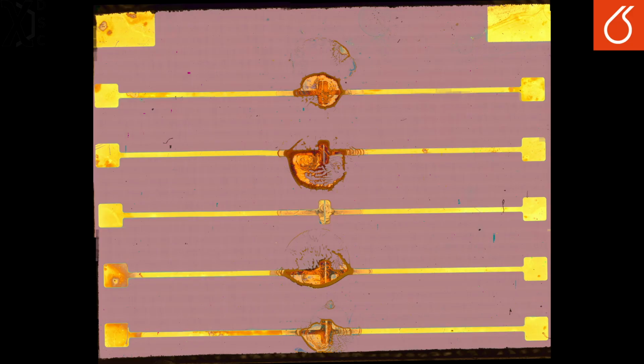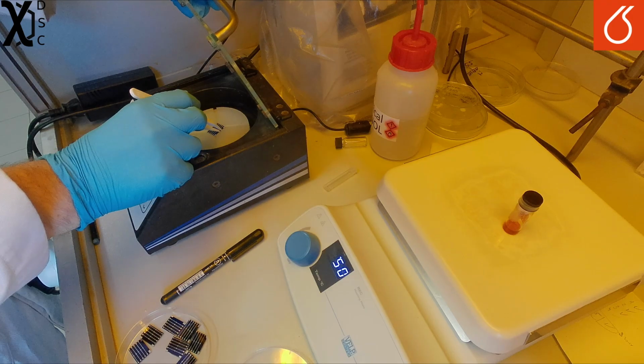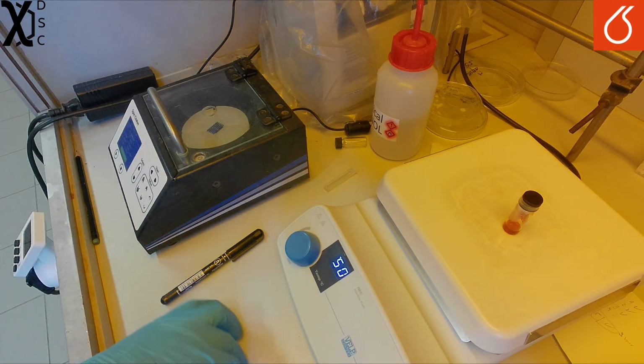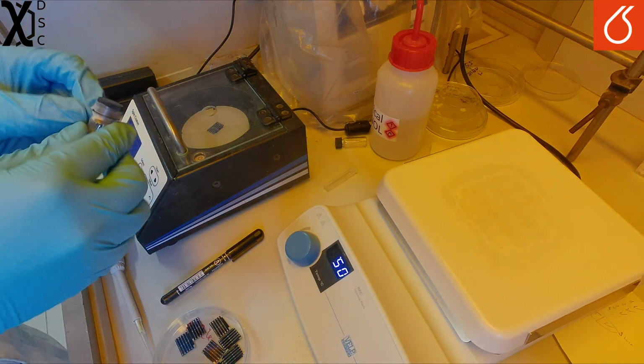A major disadvantage of drop casting is that it often produces quite inhomogeneous films. This inhomogeneity can produce numerous issues such as non-uniform charge flow and trap sites. A second approach is spin coating. Spin coating involves depositing compound in solution onto a spinning substrate. This tends to produce more uniform films.